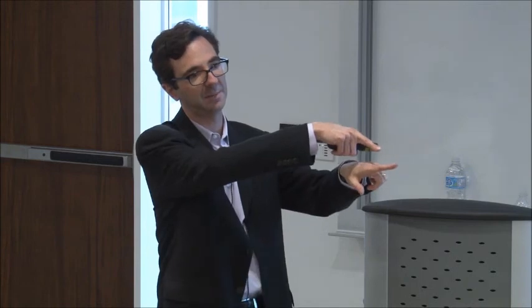And so part of the thing is the grazing has this advantage that the beam spot is very tight. So if you want to do depth profiling, you pretty much have to go to a synchrotron for these types of films because of the penetration depth of the X-rays. If you want to get your data in a reasonable time scale, because these don't scatter very strongly, you more or less have to go to a synchrotron. The scattering is very weak, and so you don't see anything. I didn't show any small angle scattering, which we do as well. It's kind of the same argument: if you're going to do small angle scattering on a polymer, you could do bulk, but if you want to do a thin film, you have to go to a synchrotron because the interaction length is...